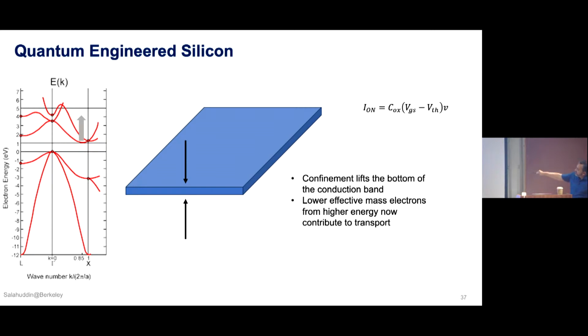It was known for a long time that if you thin down silicon, which is otherwise an indirect bandgap material, it becomes a direct bandgap material. In fact, in the late 90s, many people were very excited that this will make silicon optoelectronic, which did not happen because although it becomes a direct bandgap material, the sp orbitals don't really couple, so it's not an efficient optoelectronic material. But the fact that this indirect bandgap goes up and the material becomes kind of direct, that happens.